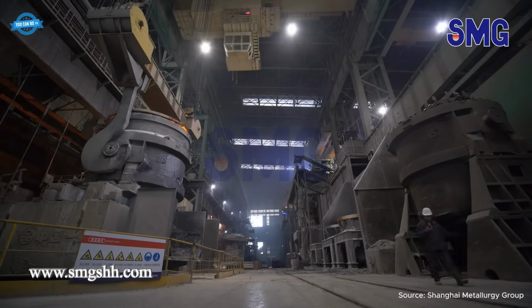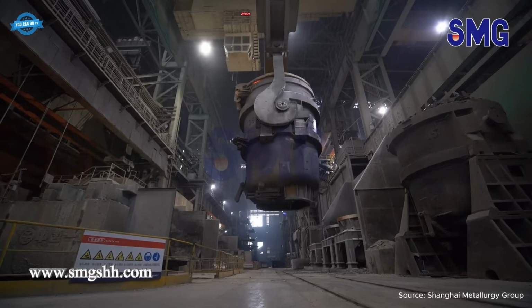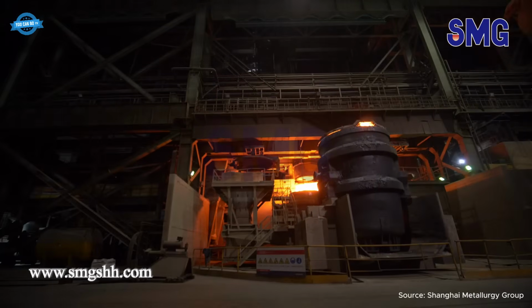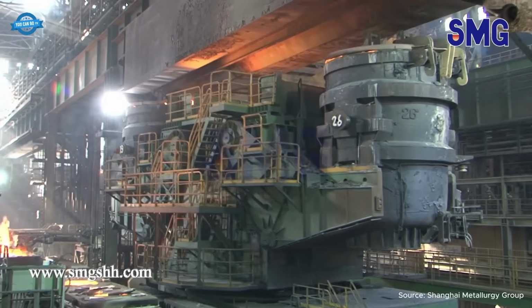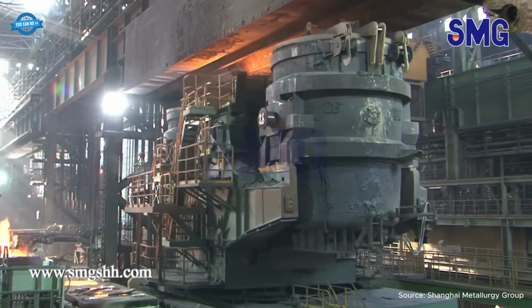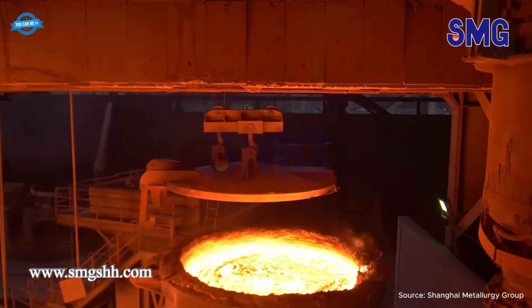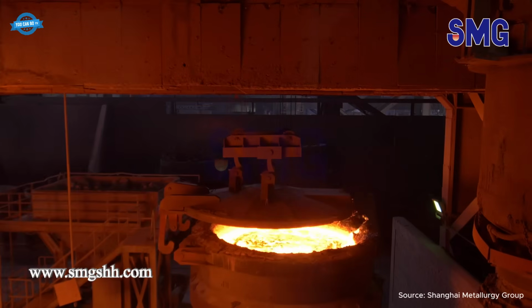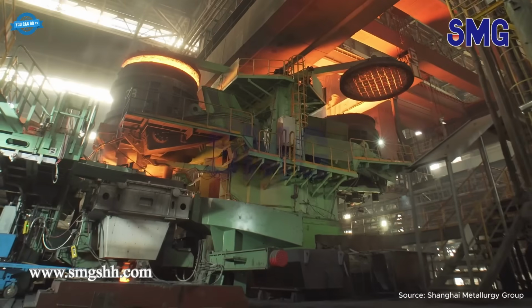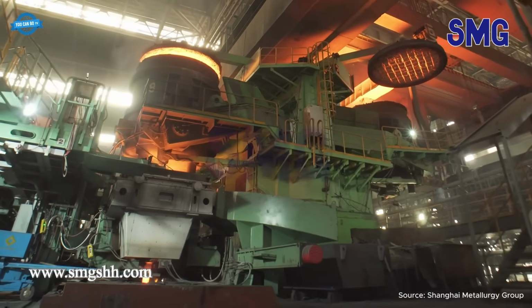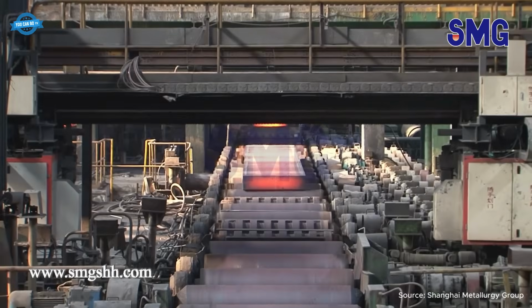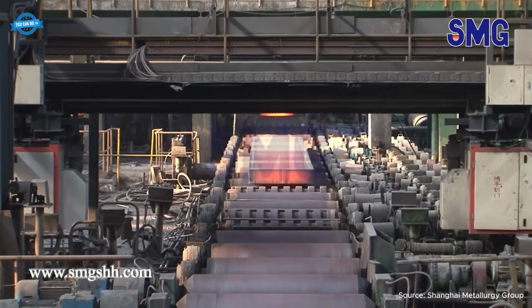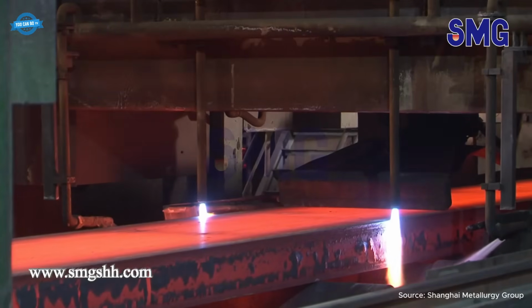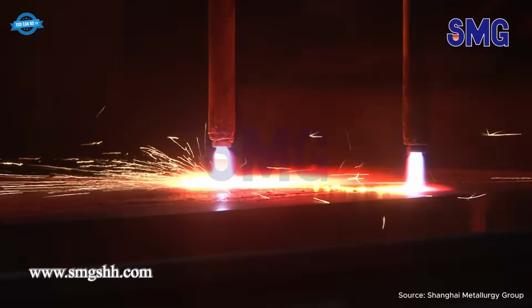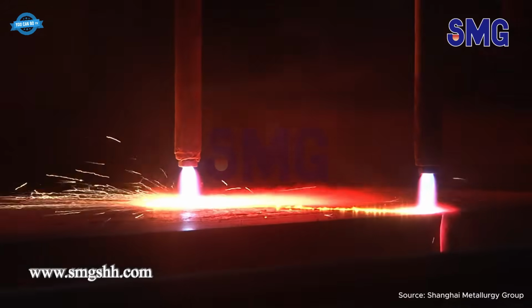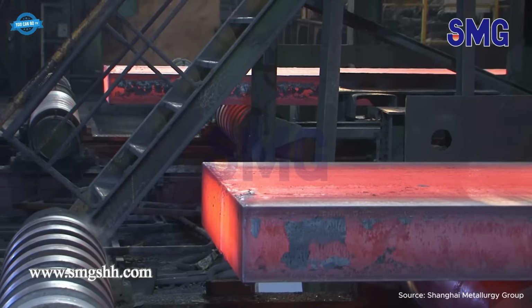Steel slab production using a continuous casting machine, Concaster, ensures high precision and flexibility. Slabs typically range from 800 to 2,500 mm wide, 150 to 400 mm thick, and 4 to 12 meters long. The system accommodates various steel grades, from carbon and low alloy steels to stainless and specialty steels. Advanced automation, electromagnetic stirring, and optimized cooling guarantee superior surface and internal quality for downstream applications.